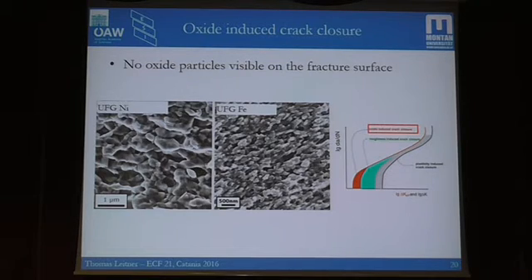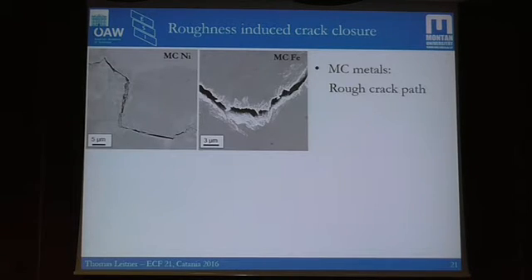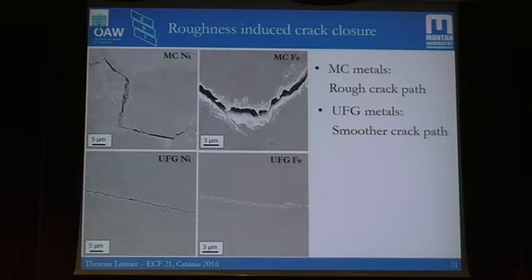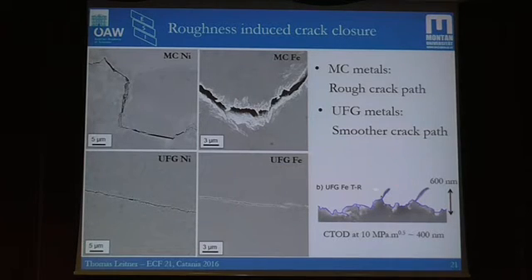So now let's have a look at why we have less crack closure contribution for our ultrafine grained metals. One possibility would be oxide-induced crack closure. However, no oxide particles or debris are visible on the fracture surface, so it's easy to think that this is reduced. It's getting more interesting for roughness-induced crack closure. In microcrystalline metals, we have quite a rough crack path, especially when we compare it to the crack path in ultrafine grained metals. From that alone, one could say, of course, then we have less roughness-induced crack closure. However, when we have a closer look at the roughness of the ultrafine grained iron, we see roughnesses and asperities in the range of a few hundred nanometers. This is comparable to or even larger than the crack tip opening displacement at quite high delta K values. So from that, we would actually expect a pronounced crack closure contribution.